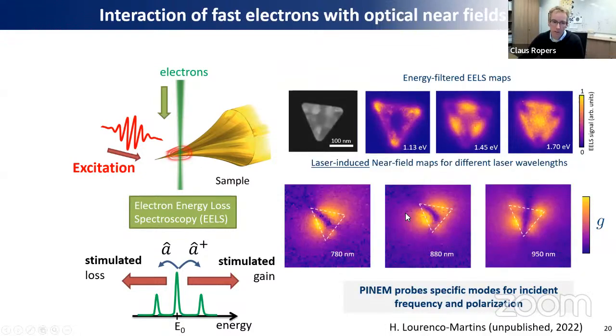Okay, and now what you can do is, besides just this electron energy loss spectroscopy, also look at other processes which correspond to the stimulated version of this process. In this way, you are probing specific modes that you excite, so you can change the optical polarization and then really look at the specific mode profile or the wavelength and track out particular resonances very specifically for a given optical excitation, basically.